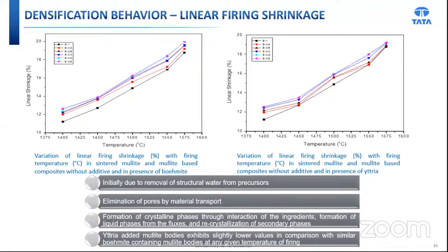With progressive rise in temperature, the increase in linear shrinkage is noticed due to the simultaneous formation of cristobalite and subsequent interaction of cristobalite with alumina to form primary mullite. Cristobalite formation increases densification, reducing the reaction path for aluminum and silicon ions, leading to an intensification of mullitization, while increasing bulk density through pore consolidation, pore removal, shrinkage, and finally grain growth.